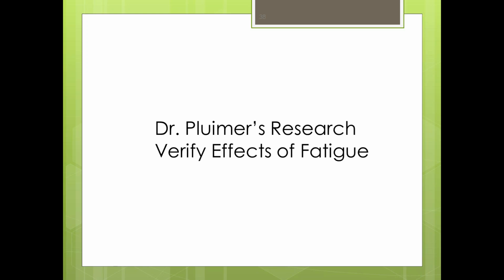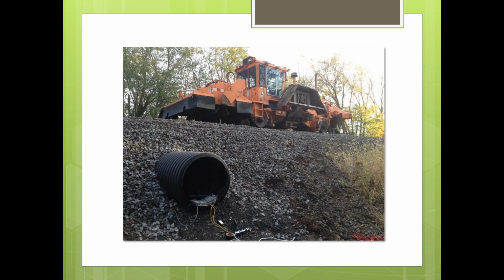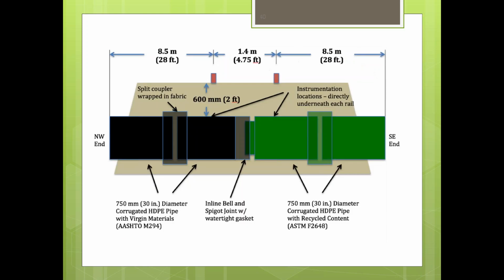So in addition to those 2 steps of research, there's also some additional research that was done by Dr. Pluimer to verify if there's any other concerns from a fatigue standpoint with recycled contents in HDPE resins. This is a photo from the project site itself, but in essence, his PhD dissertation and the research work that he did with Villanova University was really geared around creating a highly trafficked, highly fatigued, loaded situation in a commuter rail application, and trying to identify if there were any serious differences in the amount of strain the pipe was seeing from dynamic loads, and if there was any indication of cracking due to fatiguing in the recycled versus a controlled segment of complete virgin resin.